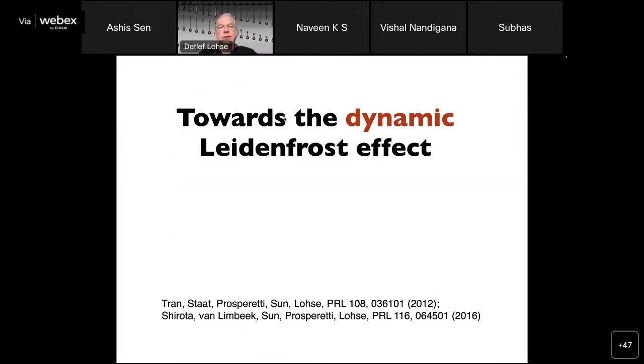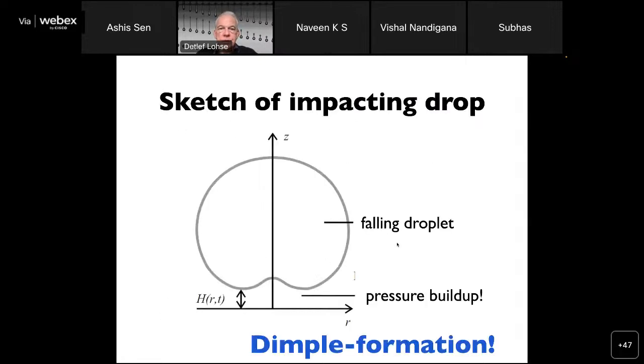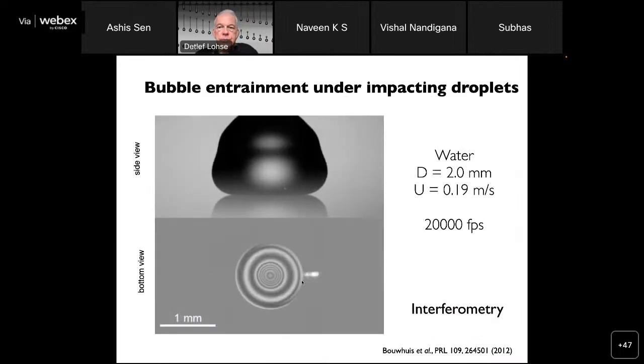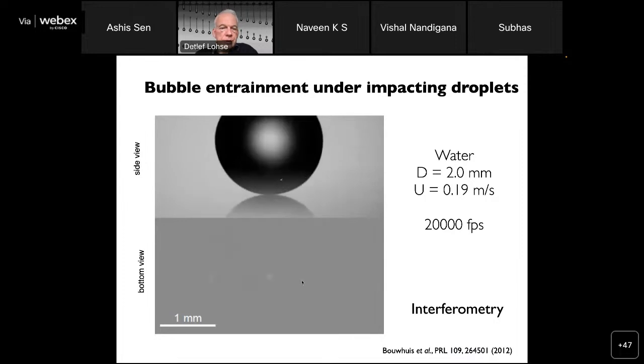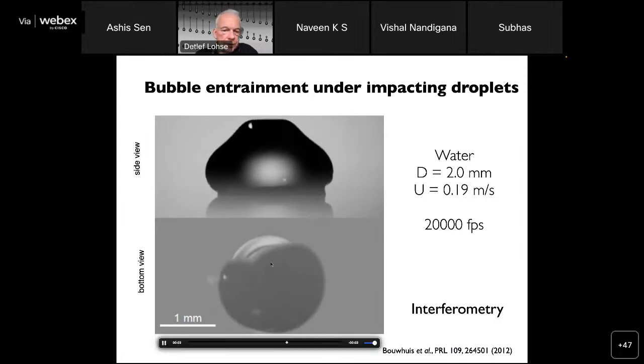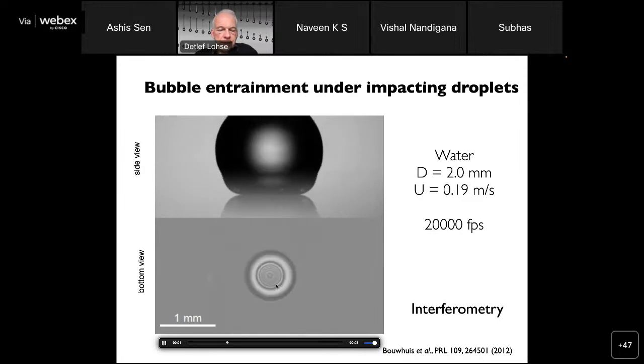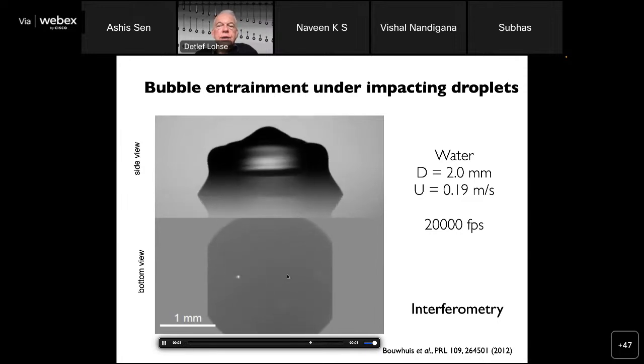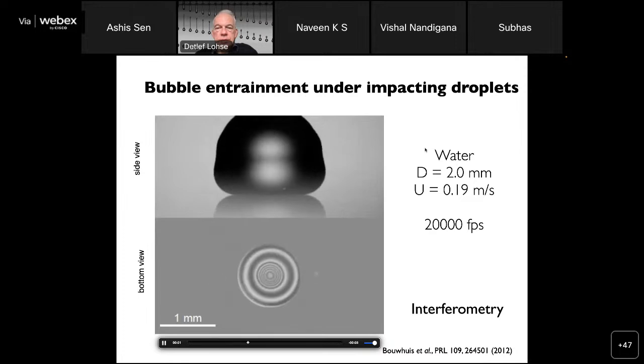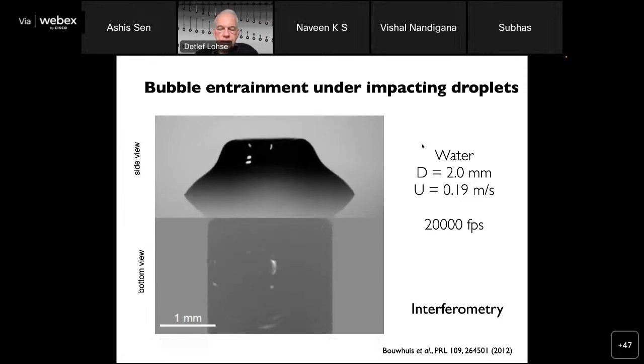So let's go to this dynamic Leidenfrost effect, and here you see some references. So here you see the sketch of this impacting droplet. And what happens is that at impact, some pressure builds up under the droplet and deforms this droplet. So you get this dimple. So here you see with high-speed interferometry what's happening. The droplet is falling. You get a dimple formation here. And out of this interferometric information, we can extract the distance of the interface.